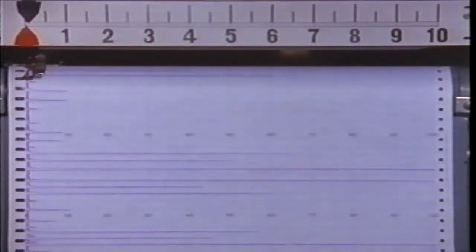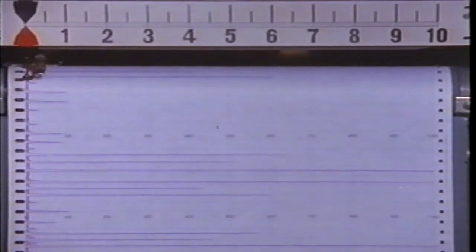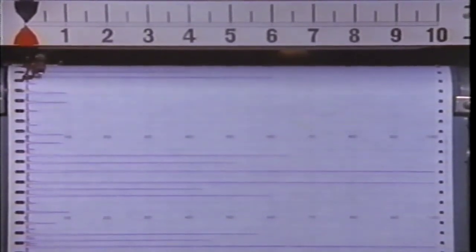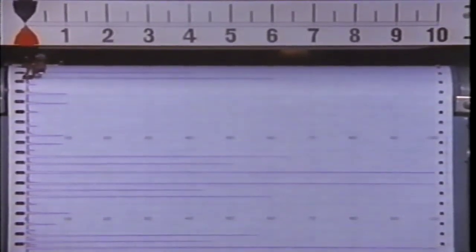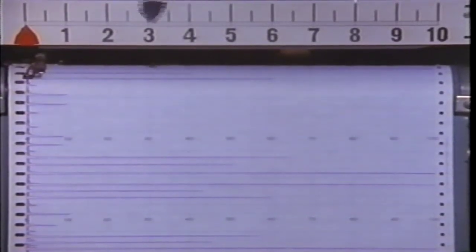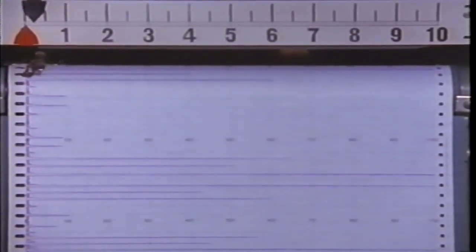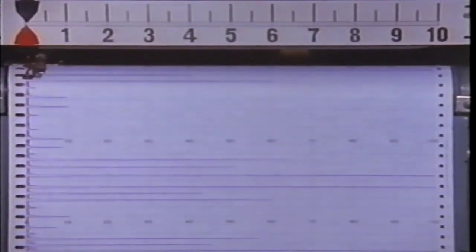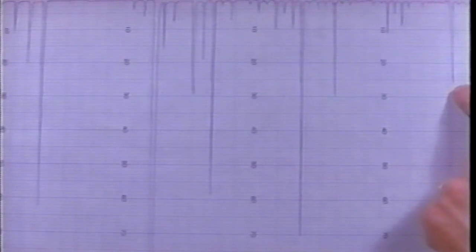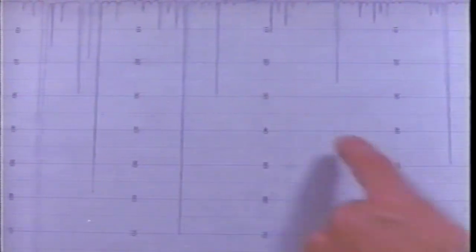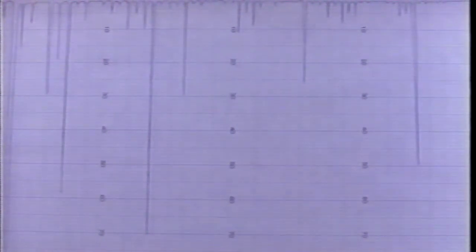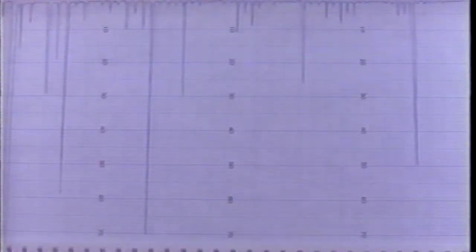The position of the peak on the chart is a key to the mass, and therefore the identity of the unknown molecule. The relative height of a peak is a measure of the relative quantity of that kind of molecule present. Most of these peaks obtained with the shutter open come from the background gases. Experiments with the shutter closed show that only these three come from the material in the hot crucible. To show these significant peaks, we have a separate tracing of the spectrum.